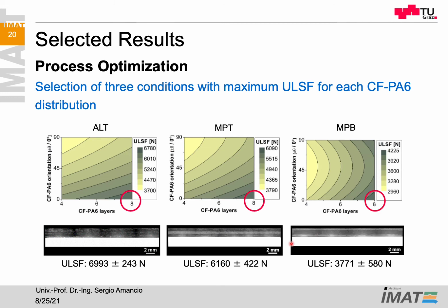And here are the results, so the cross-section overview in the overlap area of the produced specimens for the alternate, for the middle plane top, so the carbon fiber here, carbon fiber there, and all carbon fibers in the middle, in the mid plane bottom specimens. And here are the results. So we select the specimens in the area resulting the highest resistance for all of them, and then these are the tests resulting different values of ultimate lap shear force, whereby the alternate and the middle plane top are very similar, so statistically the same. So we proceeded further.